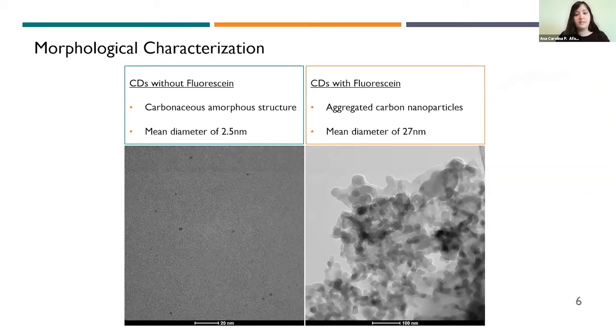Here we have representative higher resolution TEM images of both synthesized carbon nanoparticles, the first being of carbon dots without fluorescein, showing them well dispersed in an aqueous solution where you can observe a carbonaceous amorphous structure with a mean diameter of 2.5 nanometers. On the other hand, when carbon dots are coated with fluorescein, they aggregated, maintaining a size of 27 nanometers and the regular spherical aspect of carbon dots.